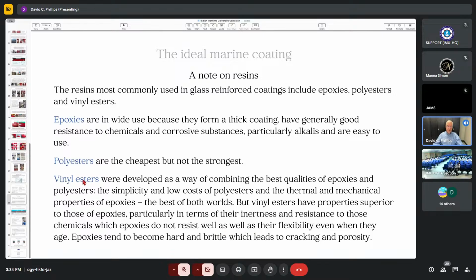Now, there's another factor with vinyl esters. If you put a coating like this on a ship, if it's brittle and hard, it will crack. When it cracks, porosity develops. The moisture gets through to the steel hull, and you've just blown your whole system. It doesn't work anymore. Epoxies tend to get brittle after a while, maybe several years, but they will become hard and brittle. And then, for example, if you tried to have one of those in the ice, the steel of the ship flexes with the ice. You hit ice, it flexes the steel, off goes your coating. It will delaminate, it will disbond if the coating is not flexible enough and adherent enough.